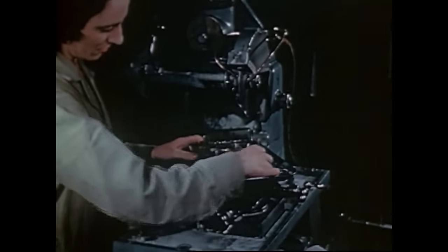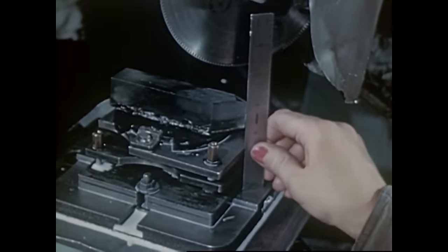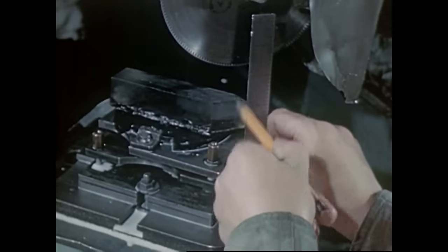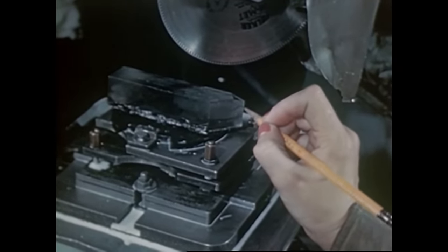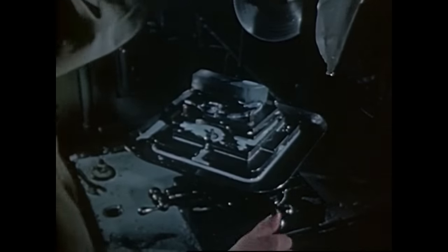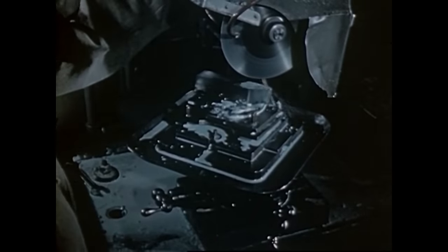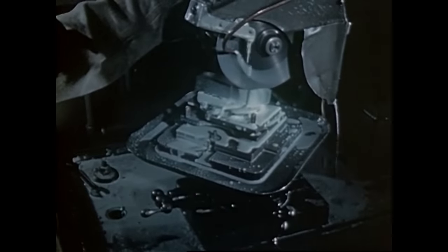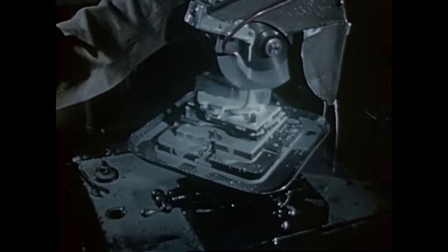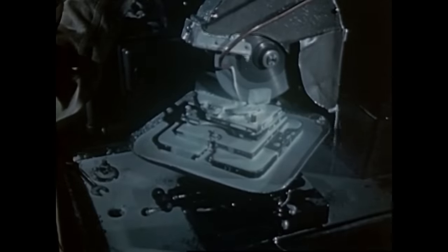After the jig is firmly bolted to the saw head, a preliminary cut is made to remove the end of the bar. And again, an identifying arrow is drawn to keep track of the up direction of the first wafer to be cut. The rough wafers are rarely more than a 1/16 of an inch thick, and it is quite an art to saw them thin and true from this hard and brittle material. The final finishing of the crystal plates to thickness will be done in grinding and lapping machines, and the time for this operation will be greatly shortened, and much material will be saved if the wafers are initially cut thin and accurately by the saw.